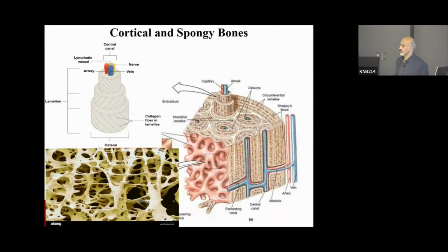The spongy bone is a network, we can say in a sense, a network of interconnected plates and rods. In the areas which we have less stress, we do expect to see rod-like structures. And when the stress is high, we see plate-like structures.